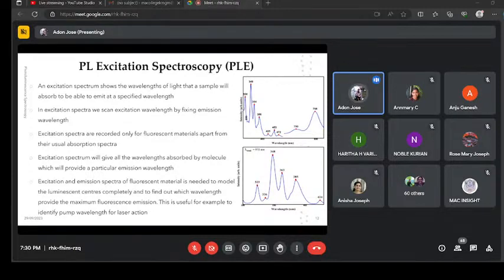In the slide, I have provided two spectra. The first one is an absorption spectrum, and the second one is an excitation spectrum. You can see several absorbance bands in the spectrum, at 324, 336, 349 and so on. Whereas when we recorded the excitation spectra of that particular material, monitoring with a fixed emission wavelength, we obtained mainly six excitation bands. It is also found to be similar to the absorption spectra. In the absorption spectra, we observed an absorbance band at 349, whereas we observed an intense excitation band at 348. And we also observed several excitation bands which are also found among the absorbance bands.